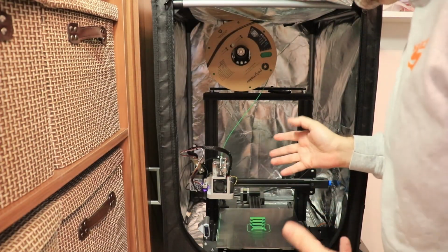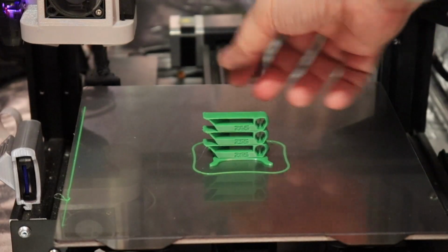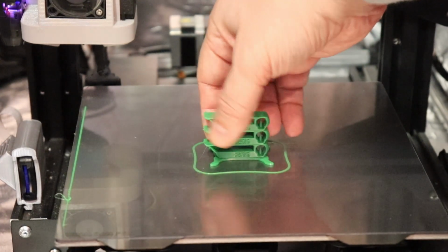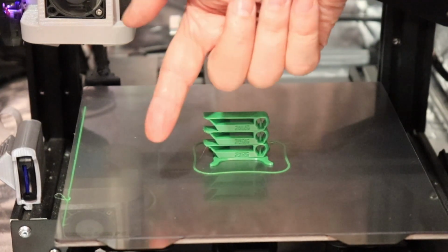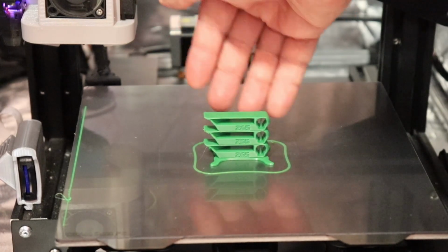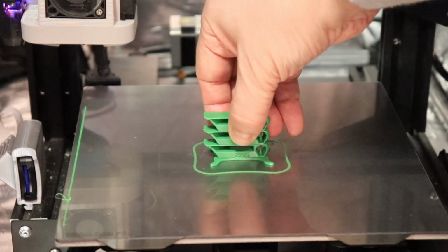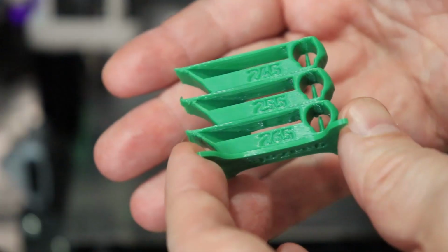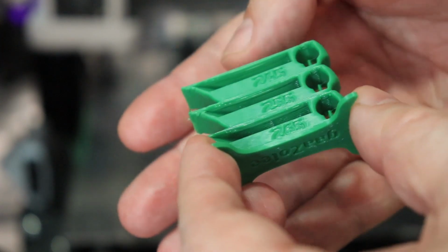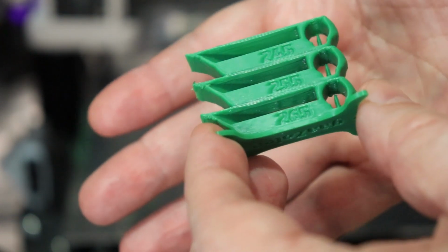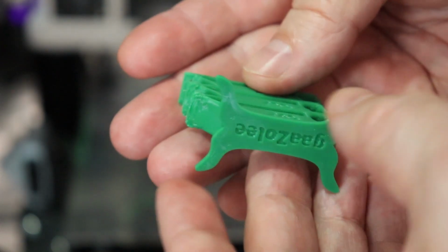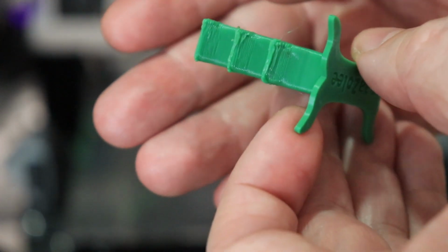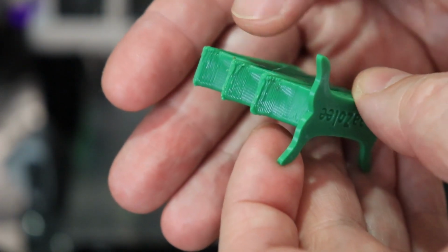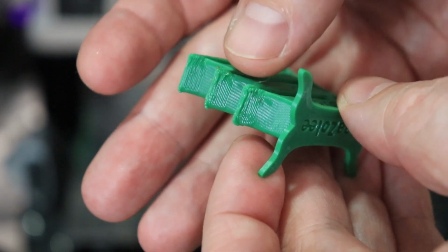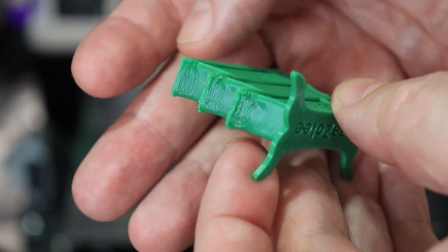There is no of that unpleasant smell of the ABS. Immediately I want to check the bed adhesion, which is great, and I know this combination of Wham Bam PEX plus the glue stick works great with every ABS and ASA. And the quality of this printing is really great. The bridging is perfect, the stringing is never a problem with ABS, and look at this overhang. On 265 it had some problems, but on 255 it was much better, and almost perfect on 245.